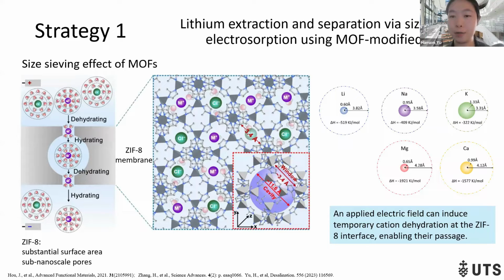Now I'd like to introduce the first strategy of my research, enhancing lithium selectivity using the size-sieving effect. In this strategy, I modified the commercial activated carbon electrode with ZIF8 type of MOF. ZIF8 is a promising material for ion separation thanks to its substantial surface area and sub-nanoscale pore windows. Its separation mechanism is based on the size-sieving effect. ZIF8 has sub-nanoscale pore windows. If we compare this parameter with the hydrated and dehydrated ion radii of lithium and its main competitors, we can find the dehydrated ions are smaller than the ZIF8 windows, but the hydrated ions are too large to pass through without dehydration.